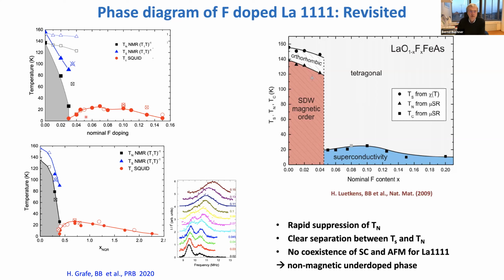And this is also seen in the more recent data. Now, meanwhile, we managed to get a smaller TN down to 30 Kelvin. So it's not this first order-like behavior, at least not for the magnetism. There we can follow it down to lower temperatures. But there is still a clear separation between magnetic order and the structural phase transition. And so the nematic phase transition and magnetic ones are well separated. And what we still have is there is no coexistence between superconductivity and magnetism. So you have this well-separated region, and you end up with a region of so-called underdoped compounds where TC increases similar to what we know from some of the cuprates.